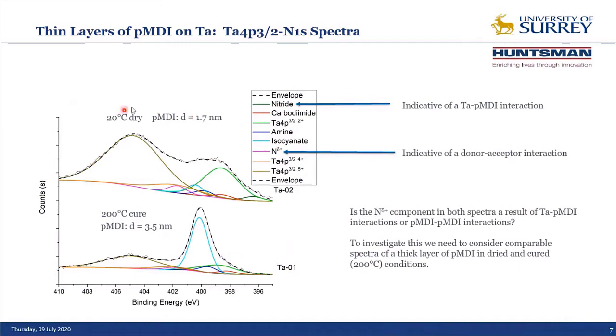However, if we go and look at the one that's been dried, where the layer is much, much thinner, we can see we've got the 2 tantalum peaks again, only much clearer this time, and we've got a lot of minor components in here. There are 2 minor components that are going to be very important to us. It's this peak here, which is at a very low binding energy, just above 396 electron volts, and that's what we've chosen to call a nitride-like component. And that's going to be indicative of a tantalum to PMDI interaction.